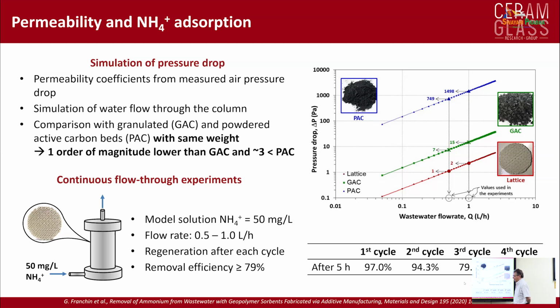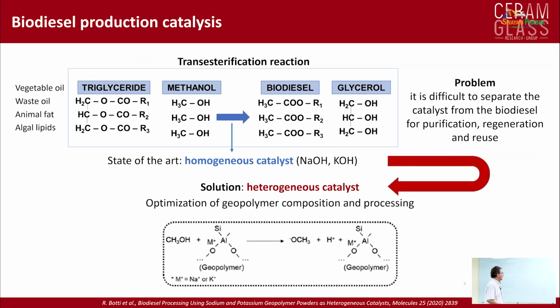And the advantage of additive manufacturing is that you can create components that have a much lower pressure drop. So at least one or two orders of magnitude lower than competing materials. So this is very favorable for practical applications. Another thing that we explored is the use of the alkalinity in the geopolymers for making biodiesel.